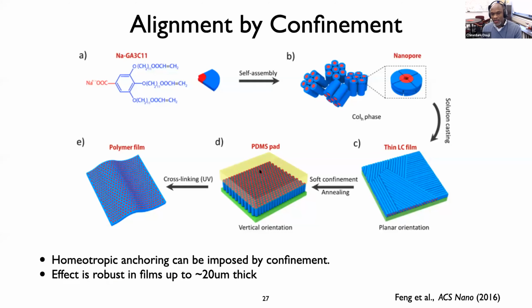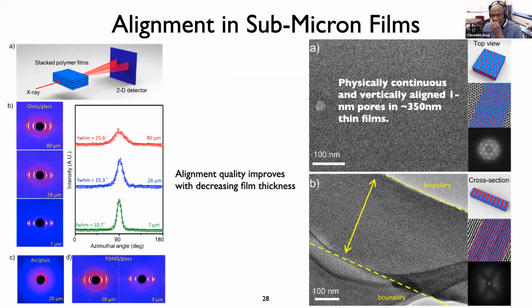We showed also that you can control the alignment of those columns by using surface confinement methods. And if you look in the cross-section by TEM of those thin films, you can see that you have those columnar structures continuous from the top to the bottom of the thin film. And this is in a film which is about 350 nanometers. And so the potential, right, one gets excited thinking that, okay, potentially this could be a workable membrane. And potentially it could be.